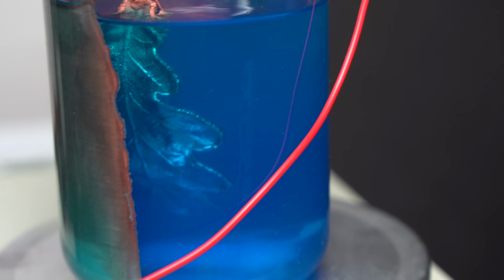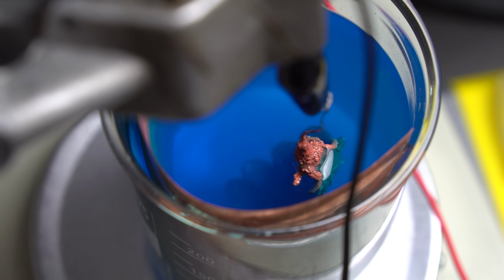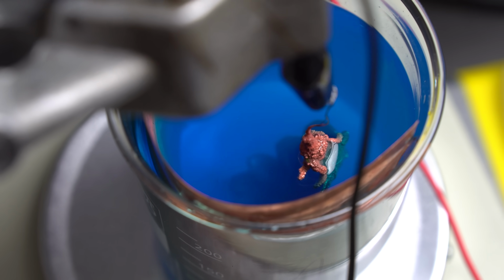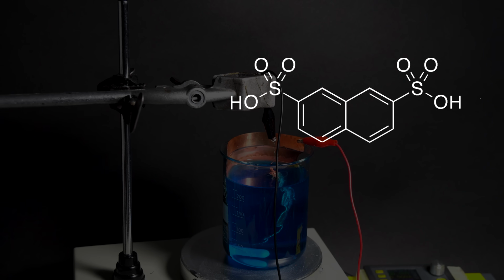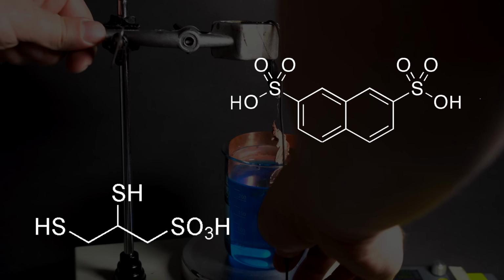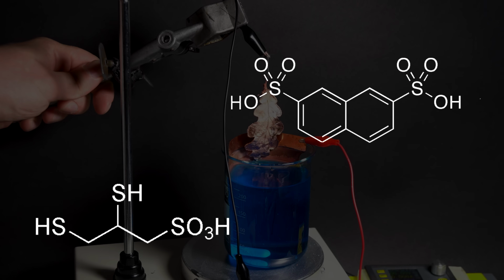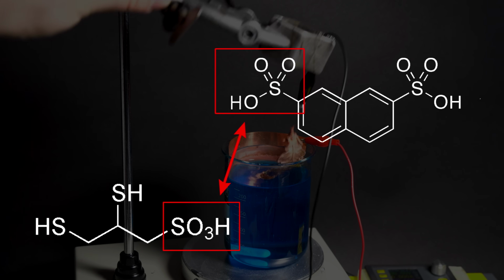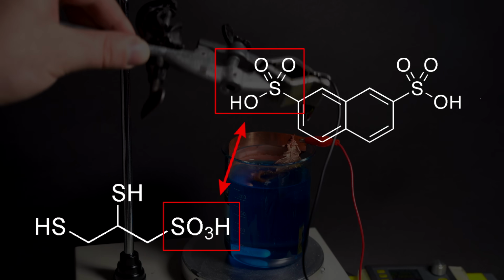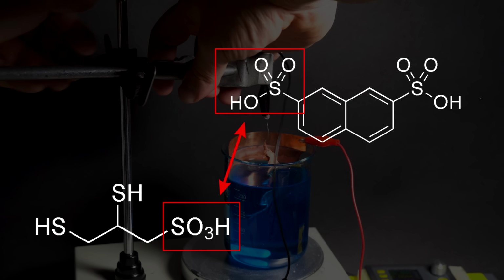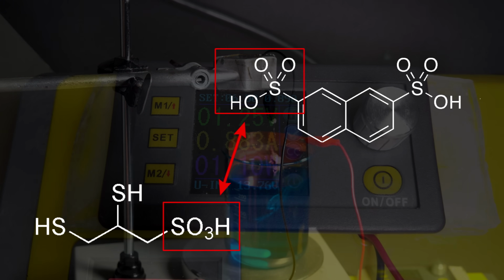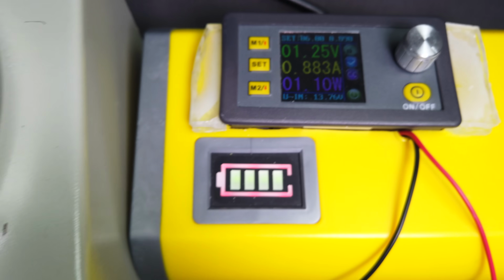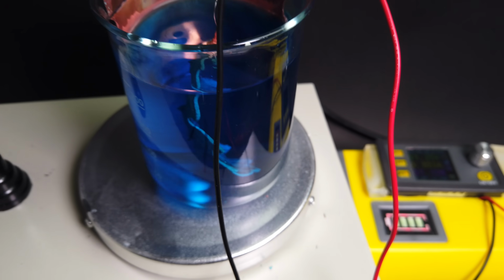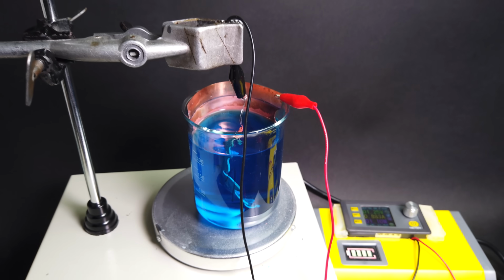Let's consider the mechanism of this reaction. Just like naphthalene disulfonic acid, 2,3-dimercapto-1-propanesulfonic acid, which is contained in unithiol, has links between carbon and oxidized sulfur, which increases cathodic polarization and also improves effectiveness of copper spreading, and also forming crystals do not grow too big in size.